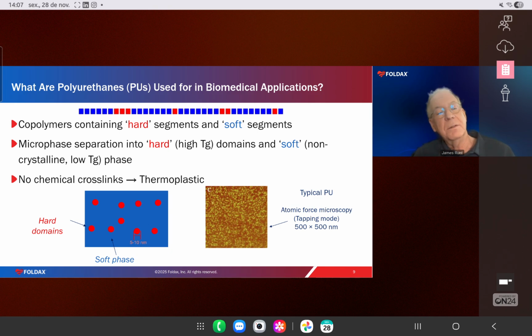The slide on the right is actually not very clear. It's an older atomic force micrograph of a typical polyurethane, basically distinguishing the brown background from the yellow dots there. The yellow is the hard segments, and the background is the soft segments. There's some better images I could have used there, but you get the idea. So we're getting segregation of the blue away from the red.